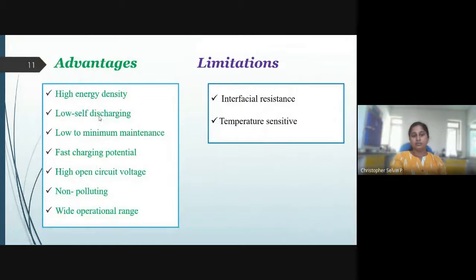The highlightable advantages of lithium-ion batteries are high energy density, low self-discharge, low to minimum maintenance, fast charging potential, high open circuit voltage compared to other batteries, non-polluting devices, and a wide range of operation under different thermal conditions, different voltage, and different chemical conditions. However, the limitations are interfacial resistance, which is the hindrance for providing long cycle life, or also to integrate this technology for further higher end applications. And also these materials are quite temperature sensitive if different chemistry is employed.